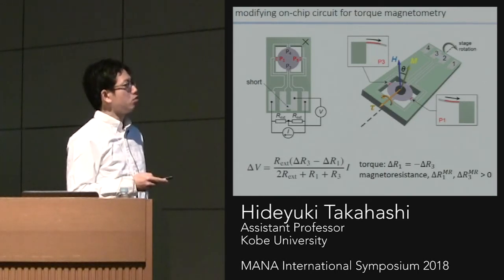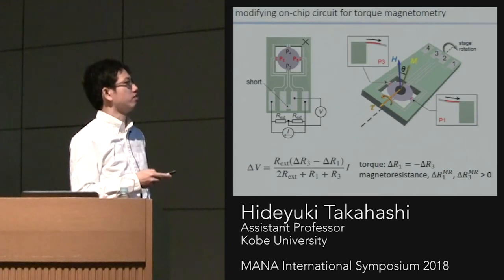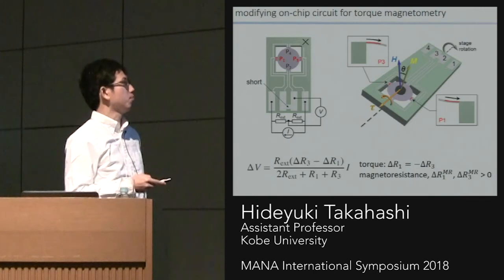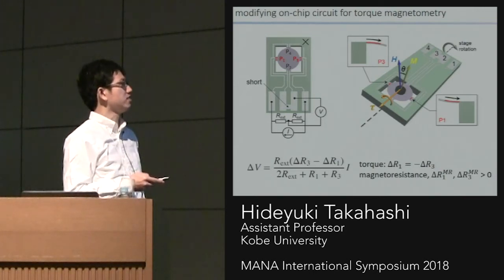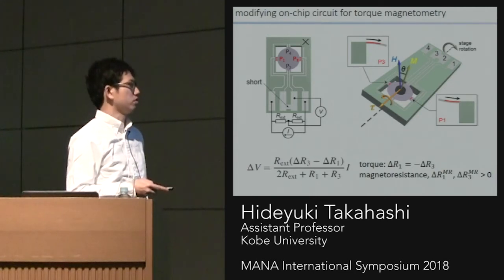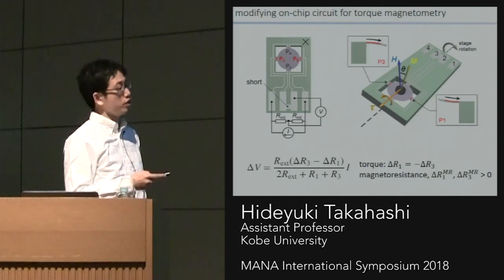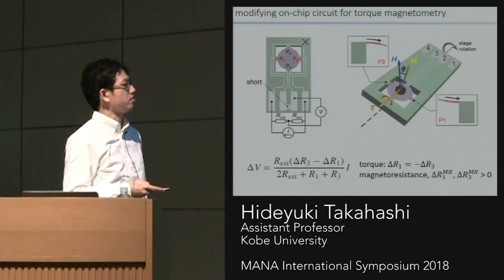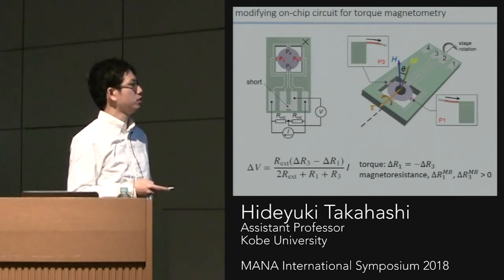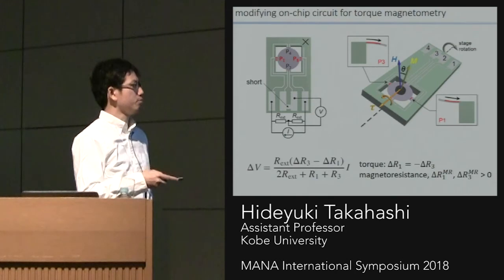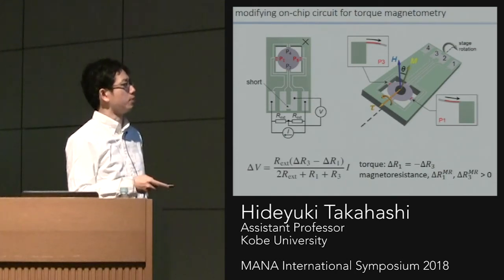When the magnetic torque is exerted on the sample, this piezoresistive change is subject to the deflection. When the P3 is pulled downward, P1 is pulled upward. So piezoresistance change is detected by forming a bridge circuit with external resistors, and the voltage signal is written as this. Here, this configuration might seem to be a little tricky, but it's important to cancel out the magnetoresistance effect. On the other hand, the torque component is enhanced by a factor of 2, so we can extract the resistance change only due to the magnetic torque.